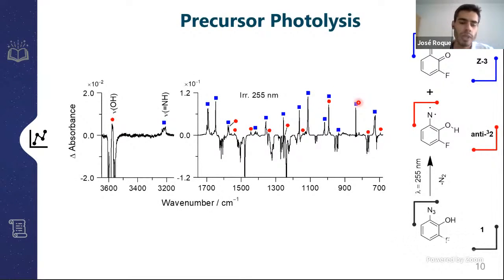So afterwards, we proceeded with the photochemical conversion of the azide by removing nitrogen gas by irradiation at 255 nanometers. And here you can see a difference spectrum, which is the spectra collected before and after the irradiation. The bands pointing downwards correspond to bands of the reactants, which are the azide, of course, and the bands pointing upwards correspond to the bands of photoproducts. And it is possible to see that the most intense bands in the spectrum were assigned to the product in blue, the final product, the aminoketone, but still we were able to detect a very small amount of triplet anti-nitrene, whose electronic ground state is a triplet state. And so we were able to verify that indeed there's a nitrene intermediating this transformation.